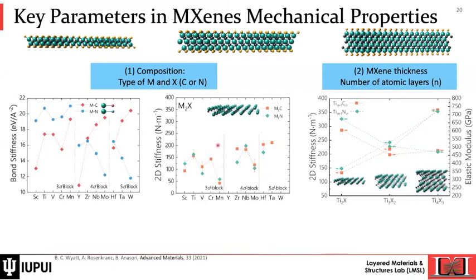You can see that there is a variation. This is based on bond stiffness. This is based on calculation without any surface termination. I will talk about surface termination in my next slide. So just by playing with the composition of transition metal and carbon or nitrogen, we can tune the mechanical properties of MXene.